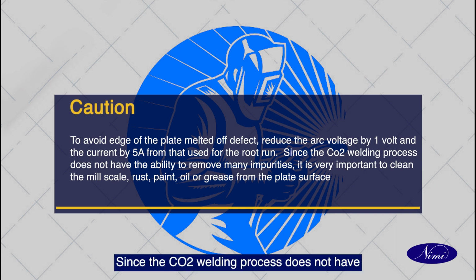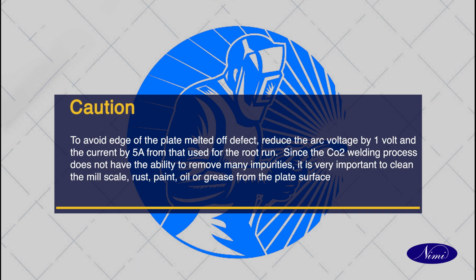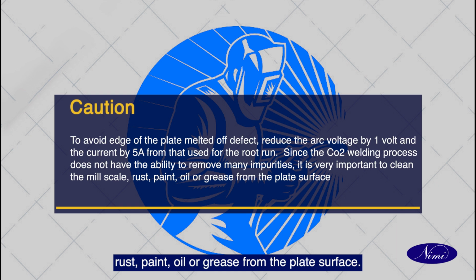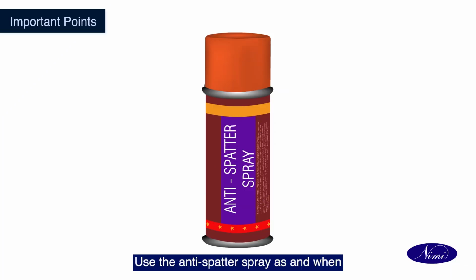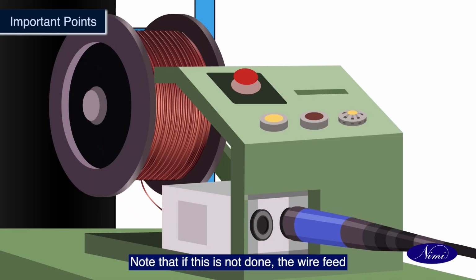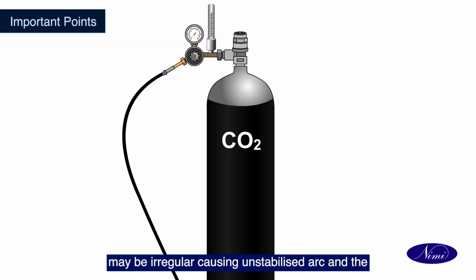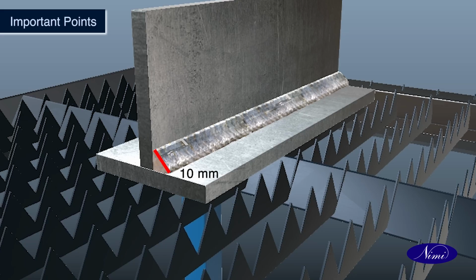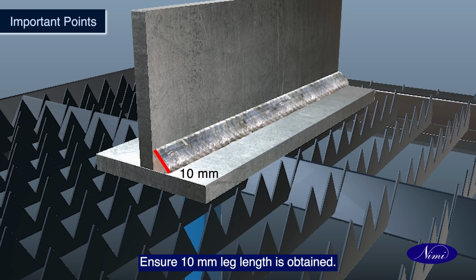Since the CO2 welding process does not have the ability to remove many impurities, it is very important to clean the mill scale, rust, paint, oil, or grease from the plate surface. Use the anti-spatter spray as and when the torch nozzle gets clogged with weld spatters. Note that if this is not done, the wire feed may be irregular, causing unstabilized arc, and the CO2 gas flow will not be uniform, causing atmospheric contamination of the weld and porosity. Ensure 10 mm leg length is obtained.